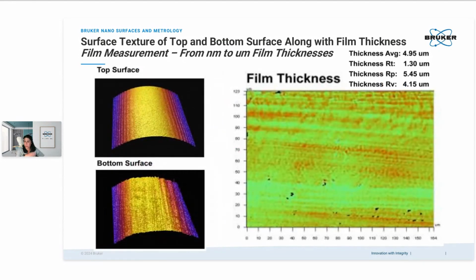A further big advantage of this way of measuring, as you can see in this example, is that not only the thickness of the film can be measured with all the parameters like average and roughness parameters of the film. You can also get within the measurement the top surface, as well as the bottom. So you can also have the information along the whole film thickness measurement and get all the detailed information about that. And in case you want some further information on film measurement, you can also find afterwards in the symposium, in the download area, an app note about film measurement.